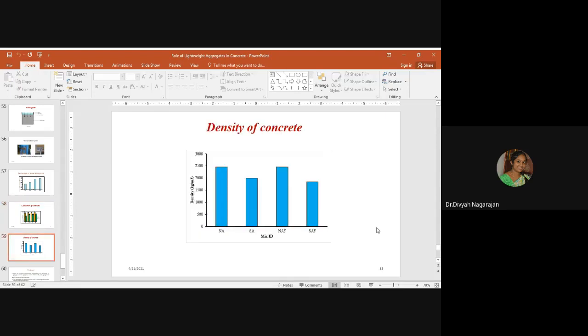Density of concrete. Speaking about the density of the concrete, the sintered fly ash aggregate had a dry density of about 895 kg per meter cube, whereas the normal aggregate is 1,625 kg per meter cube. The normal aggregate concrete had a higher density, that is the usual density of about 2,500 kg per meter cube, and basalt fiber is lightweight in nature, and being lightweight in nature, it did not affect the density of the concrete, which is the intended property of a structural lightweight concrete. This is why basalt fiber is used for this purpose.